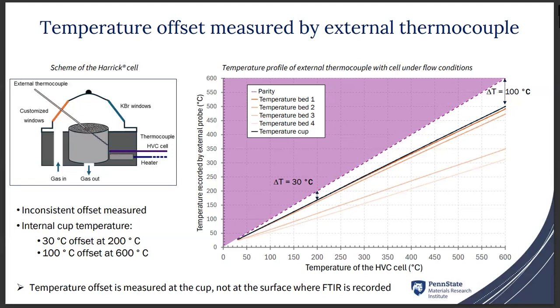What we have done at the end was to put the thermocouple inside the cup, touching the sample cup. This is the maximum temperature you can achieve, because it's the temperature in contact with your powder. Even doing that, we have a difference of 30 degrees Celsius at 200 Celsius set, and 100 Celsius when we set the temperature to 600 degrees Celsius. So this is a good approximation, but it doesn't tell us the temperature at the surface we're analyzing, just what is the temperature inside the cup.